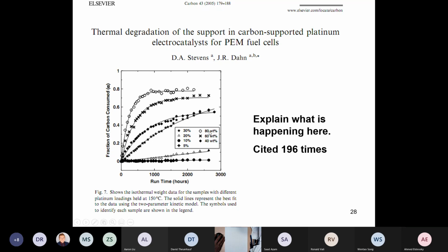And you can see that with 80 weight percent platinum, you lose almost all your carbon in 500 or 600 hours. It just burns away. Now, if you have any experience with carbon and graphite, and you heat it at 150 degrees C in air, it doesn't do a damn thing. But in the presence of a really good catalyst, it just reacts and creates CO2. So we were really quite blown away by this. And you can see that only the samples that had, here we are with 20 weight percent, not much is happening. And at 10 and 5, they're pretty stable. There's not much weight loss going on. We just don't have enough catalyst there.